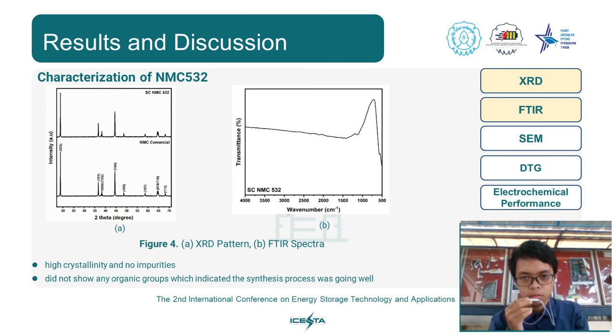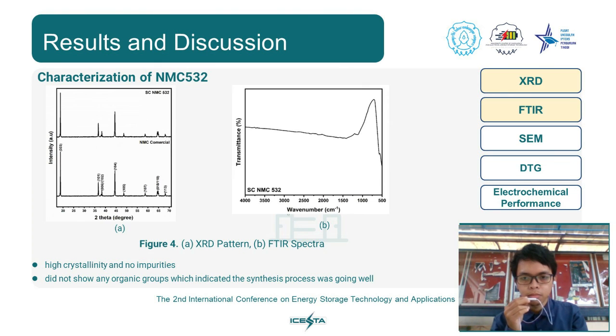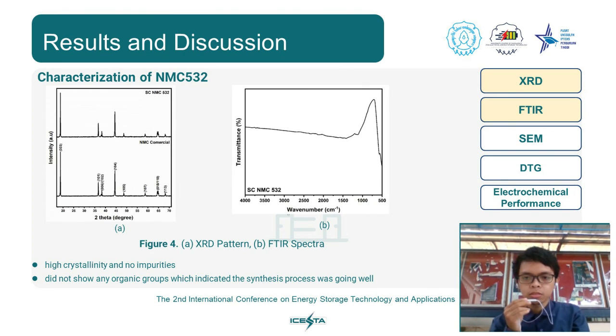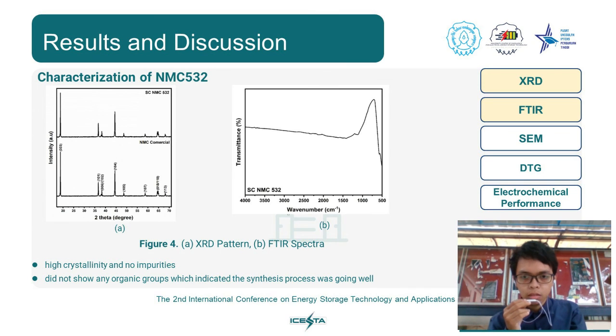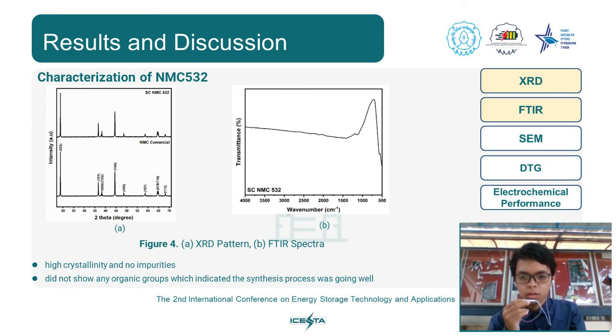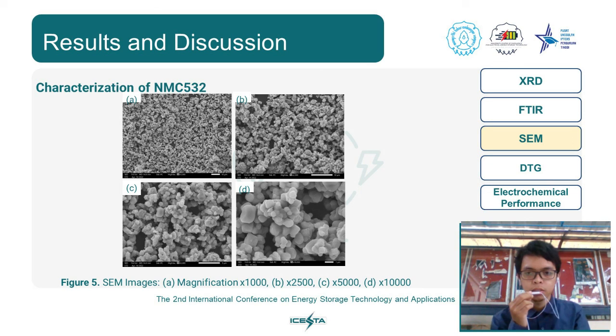And the next slide is the characterization of NMC532 material as the final product that we synthesized from mixed hydroxide precipitate. From the XRD pattern, we compare it with commercial NMC532 material, and we can conclude that there is high crystallinity and no impurities in our product. And the FTIR spectra didn't show any organic groups, which indicates that the synthesis from mixed hydroxide precipitate to NMC532 went well. And the next is the characterization of NMC532 material using scanning electron microscopy at various magnifications.